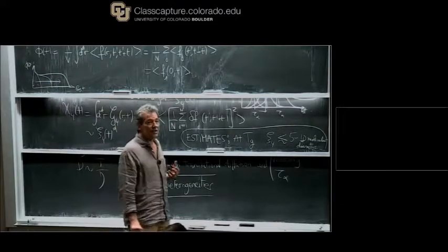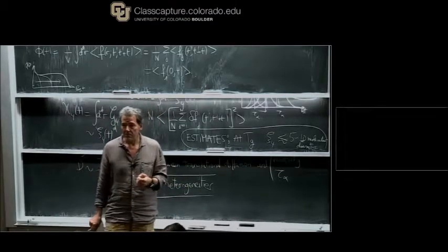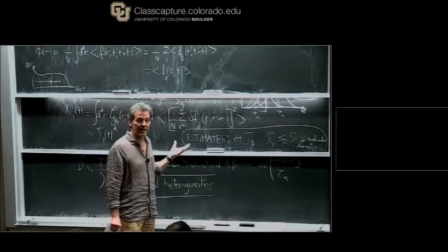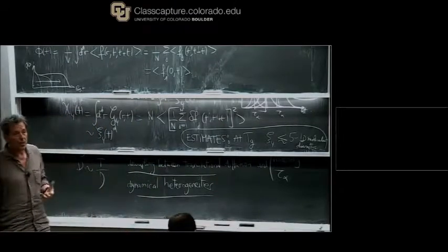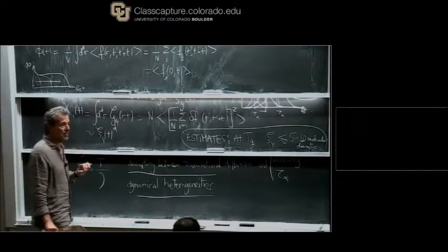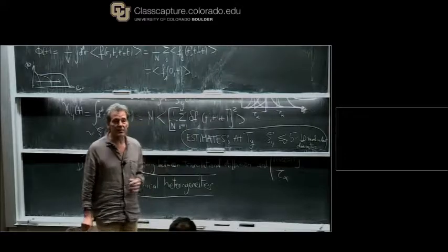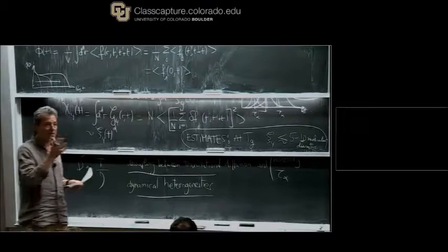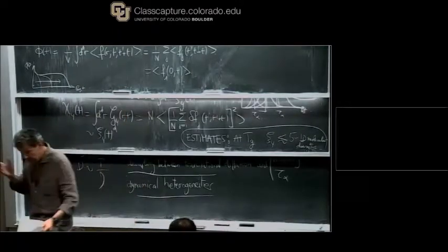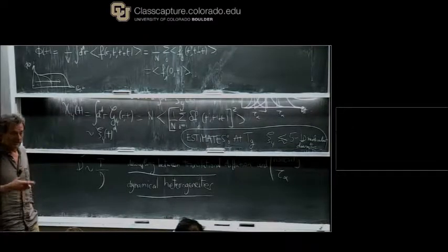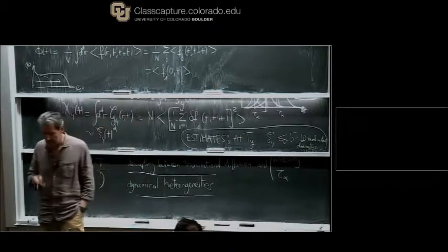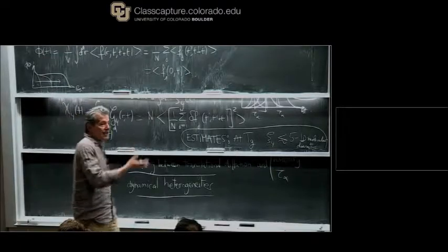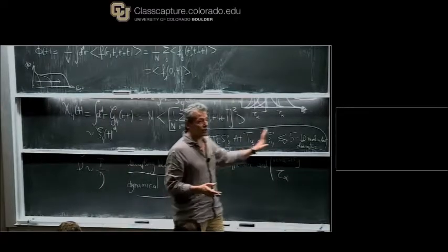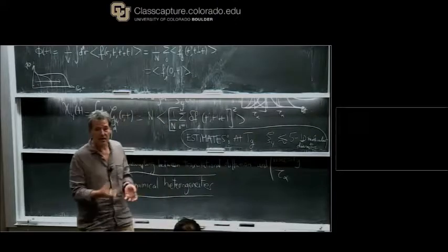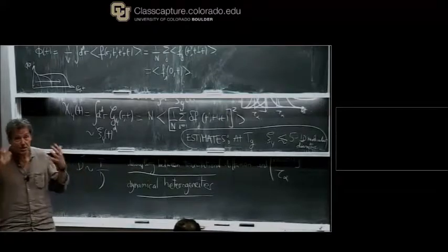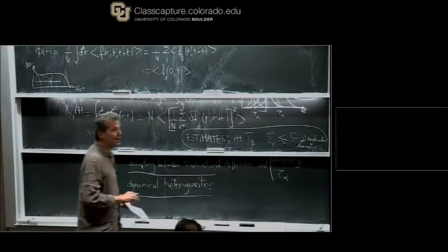And for instance, even in strong glass formers, which have Arrhenius temperature dependence, you would nonetheless expect to have heterogeneous dynamics. Something more intrinsic to slow dynamics, rather than something that directly correlates with the super-Arrhenius temperature dependence of the alpha relaxation time. This is a little subtle, and it's not proven, except maybe in some mean field limits, that there is necessarily no direct connection between those growing correlations and the super-Arrhenius dependence of the relaxation time, of the slowing down. This is just to keep in mind. I'm not proving anything, I'm just telling you this.